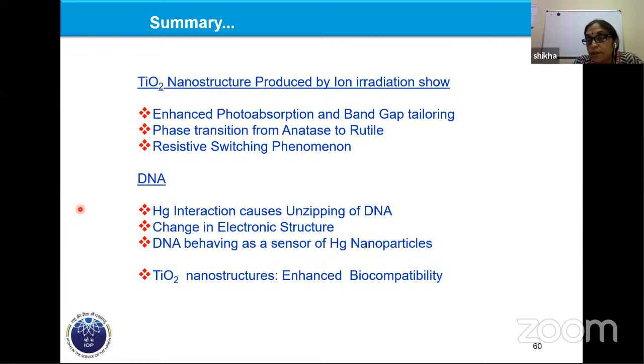So the efficiency of both also will be in between, but TiO2 in general shows a good efficiency for photocatalysis, like splitting of water. Of course, the efficiency is not good. It's only 5%. And the one I showed you was more for the N-type TiO2, which had some kind of vacancies in that. Oxygen vacancies were present. So in principle, how the efficiencies change will be measured together. Separately anatase and rutile have been measured, but the compound will be in between the two efficiencies.